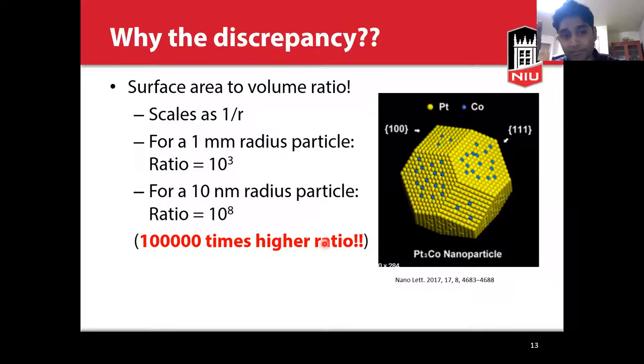And for a 10 nanometer radius particle, the ratio comes out to be 10^8. So that's 100,000 times larger than what you would find for a 1 millimeter radius particle. So if I have the same weight of these two particles, the implication is that I have more surface atoms for the nanoparticle compared to what I would find in a 1 millimeter radius particle. Now, the properties of these particles are determined by the surface atoms, because you have more fraction of them covering the surface compared to a large particle, where it's mostly dominated by the bulk properties. And it turns out that surface atoms are more reactive in nature.